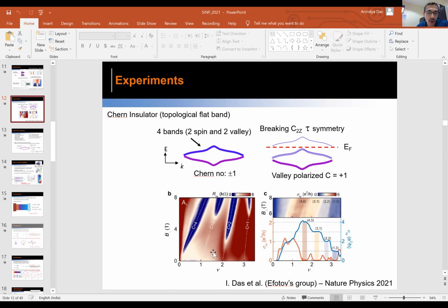But having said that, there is a catch. All this Chern quantization, what you see at large magnetic field, as we discussed, there are symmetry-related valleys with opposite Chern number. Unless you break some symmetry, you cannot see a resultant effect. Because there are two valleys which have opposite Chern number, the result is zero, so you have to somehow break this symmetry. Either you put a different chemical potential, or you use a boron nitride potential, which breaks the inversion symmetry. For example, if you align with boron nitride, you can break the inversion symmetry. Or they use a magnetic field, so you break time reversal symmetry. But you can ask, why do I need such a large magnetic field? These questions are not answered, because in principle, if you can break this C2z symmetry at zero magnetic field, you can see this Hall response, but that has not been seen yet.